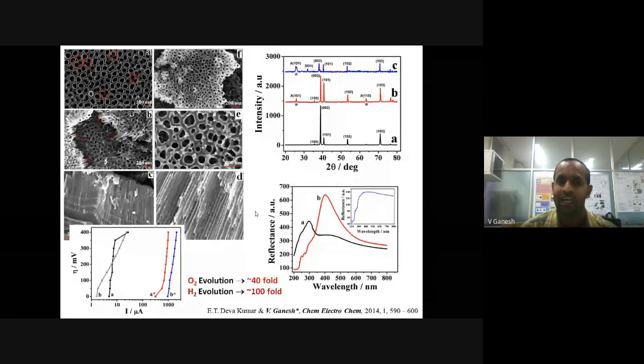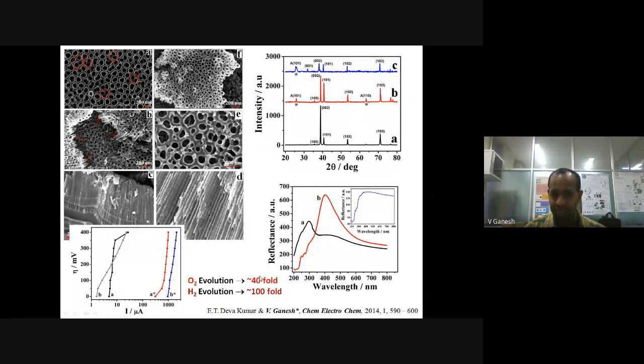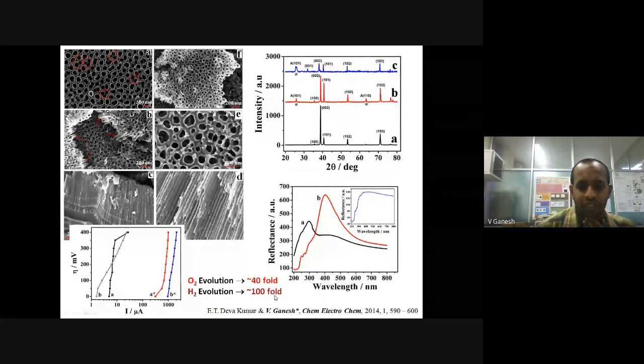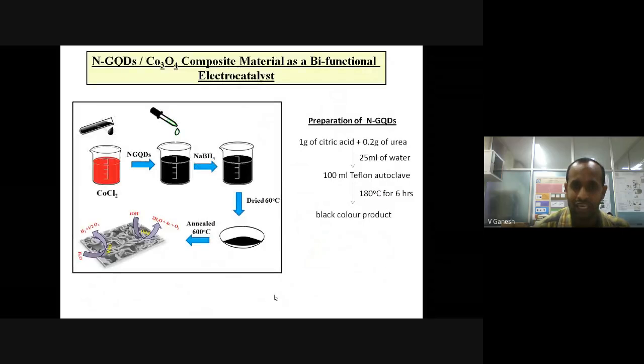Rather than photocatalysis, even by applying a voltage itself, you can play around by tuning the band gap simply by applying a potential. So you can see that the oxygen evolution is enhanced by about 40-fold, and similarly hydrogen evolution is enhanced about 100-fold compared to the normal catalysis.